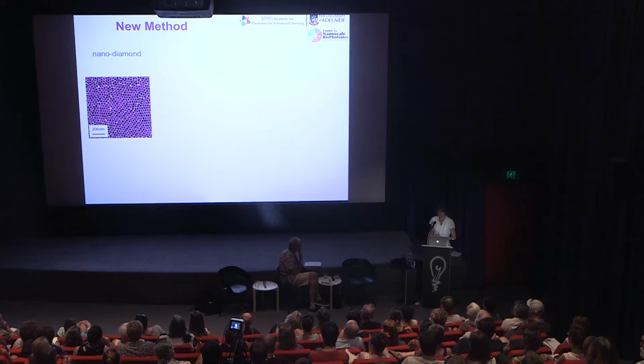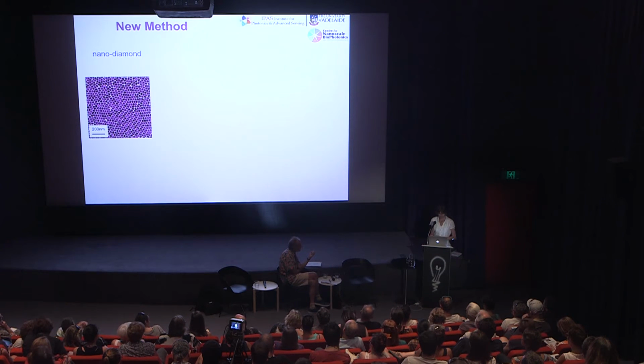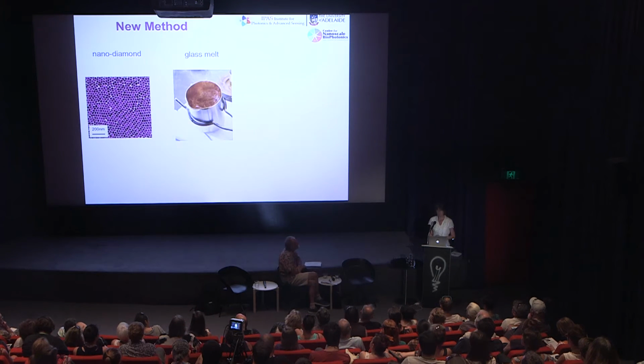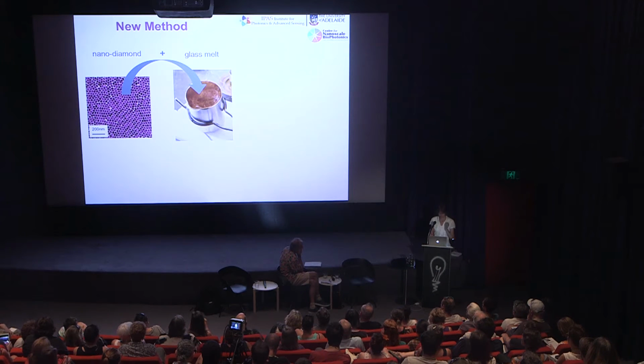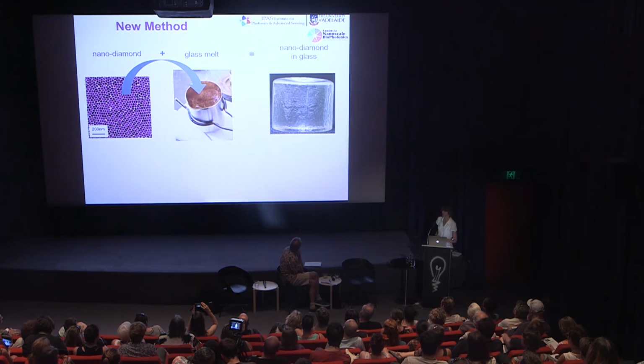And scientists are control freaks. We want to have absolute control of the processes. And so, 3-4 years ago, in collaboration with a few people, we came up with a new concept. We start with having the nanocrystals already made. In this case, it's nanodiamond, again in the order of 50 nanometer. We make a clear glass melt, and then we throw the nanodiamond into the glass, stir for 3 to 10 minutes, and then we cast it. In this way, we can achieve a glass which contains the nanodiamond.